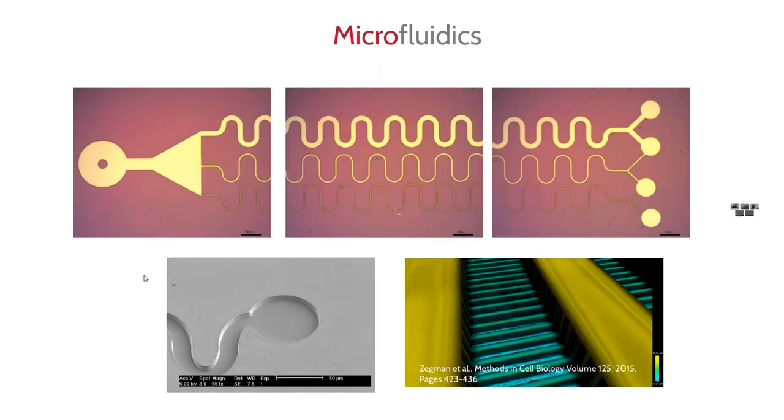Microfluidics is a popular field of research where the MicroWriter reveals itself a very useful tool. We can expose very thick negative photoresist, and some of our customers regularly work with thicknesses of resist above 100 microns. The possibility to have a 365 nanometer light source makes the system compatible with SU8 resist, which has become a reference resist in the field of microfluidics.